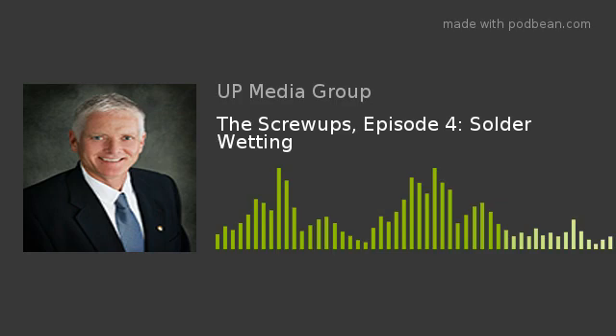In the case of a non-wet condition, we might recommend a different product, something that's got more activity. But whenever we change the chemistry to accommodate something like that, our world is a this-for-that, a quid pro quo. Anytime I increase the activity of a product, of a flux, and I'm referring to solder paste pretty much specifically, we increase its reactivity. So solder powder and flux medium are in a jar. We refrigerate them to slow down the chemical reactions between the flux medium and the metal powder. Take it out of the fridge, allow it to come to room temperature. Those chemical reactions start to accelerate due to the increased temperature, and then you stick it in an oven, and those chemical reactions explode, and everything happens really, really fast.